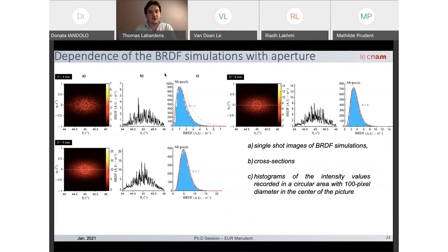And when we remember the experiments, we have almost the same orders as before, except for the last measurement, but we have a small uncertainty about the order, but we are still very close to the same order. And we can say with confidence that the effect that we are seeing is indeed speckle.